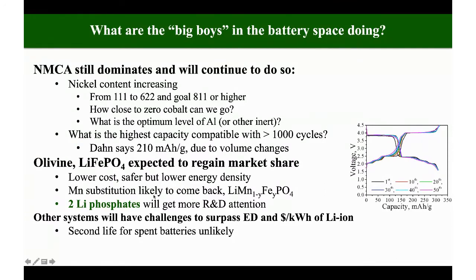And what we're trying to do is develop these 2 lithium phosphates. And I think this will get more R&D attention. And I'll show you on the right-hand side here, this is our data on this vanadium phosphate. So you get one plateau just under 4 volts. So this is vanadium 5 to vanadium 4. Then another one for vanadium 4 to vanadium 3.